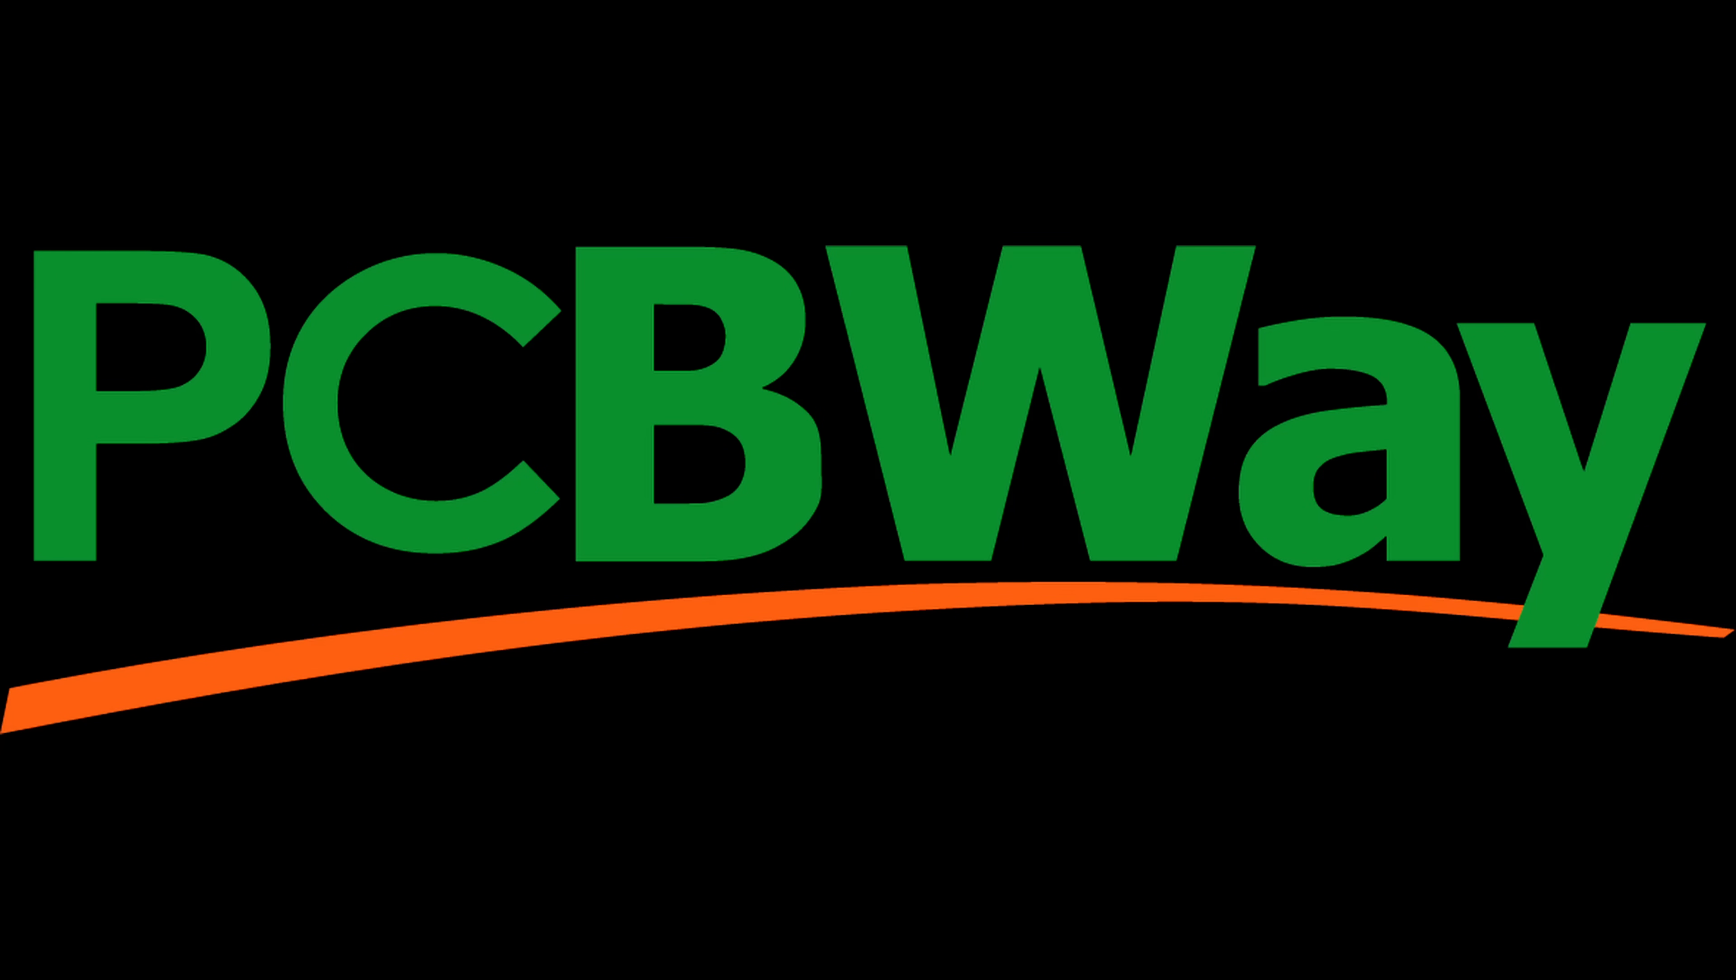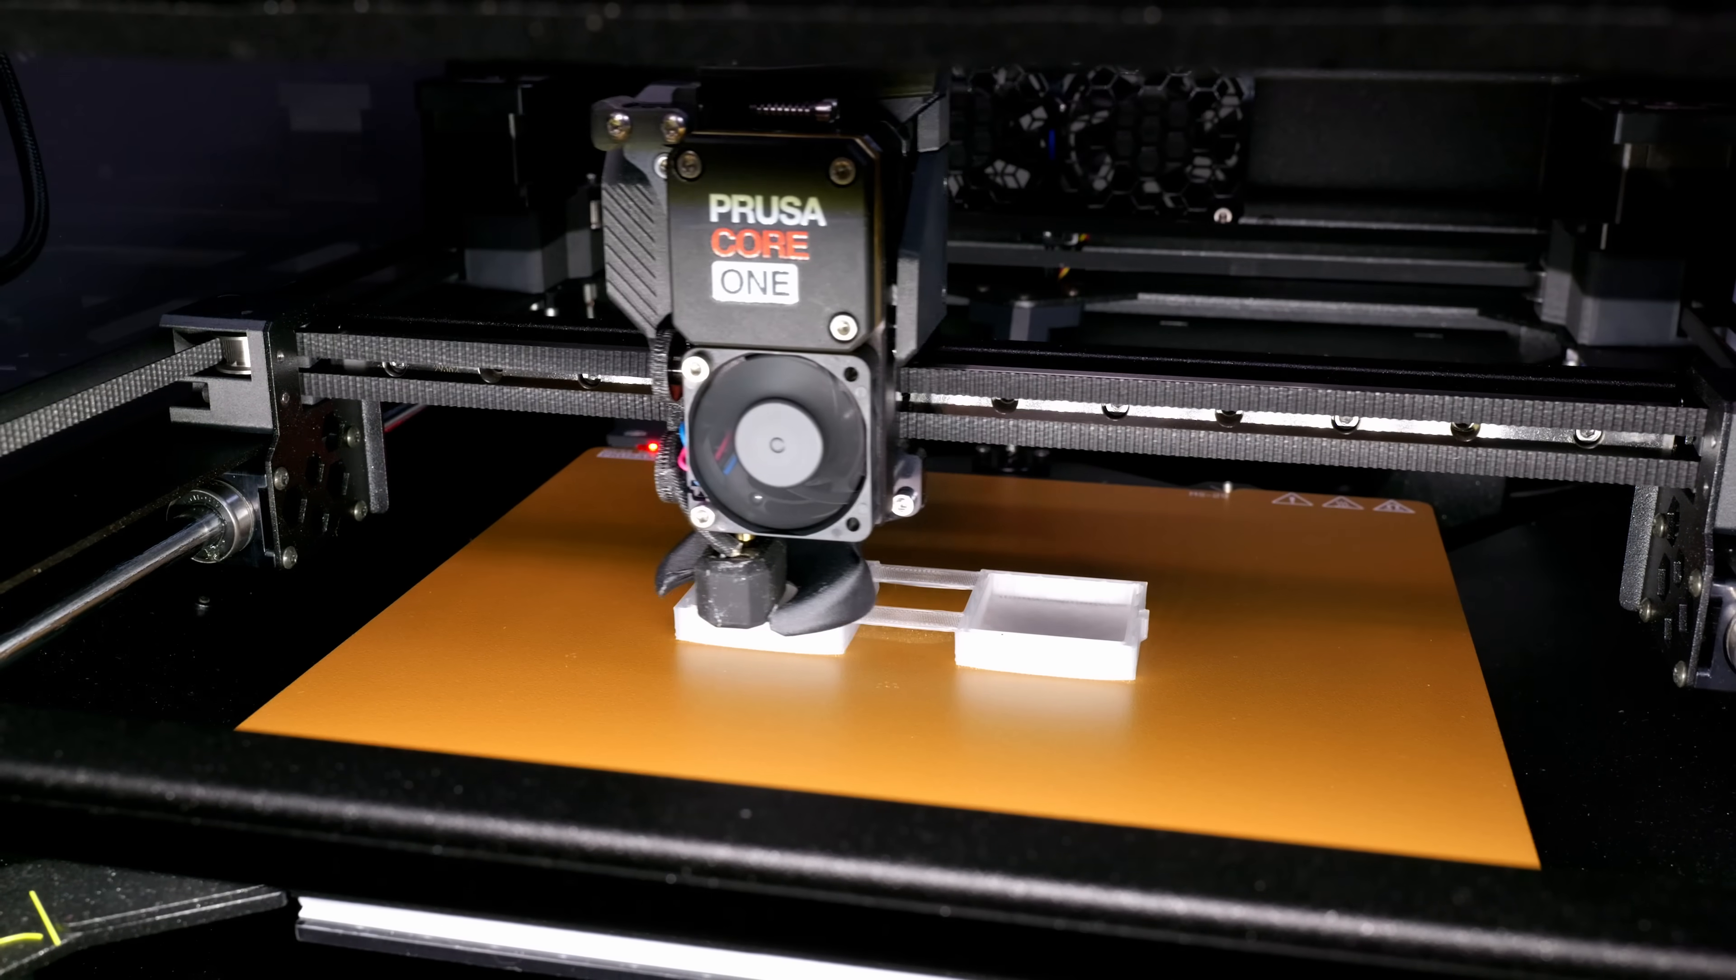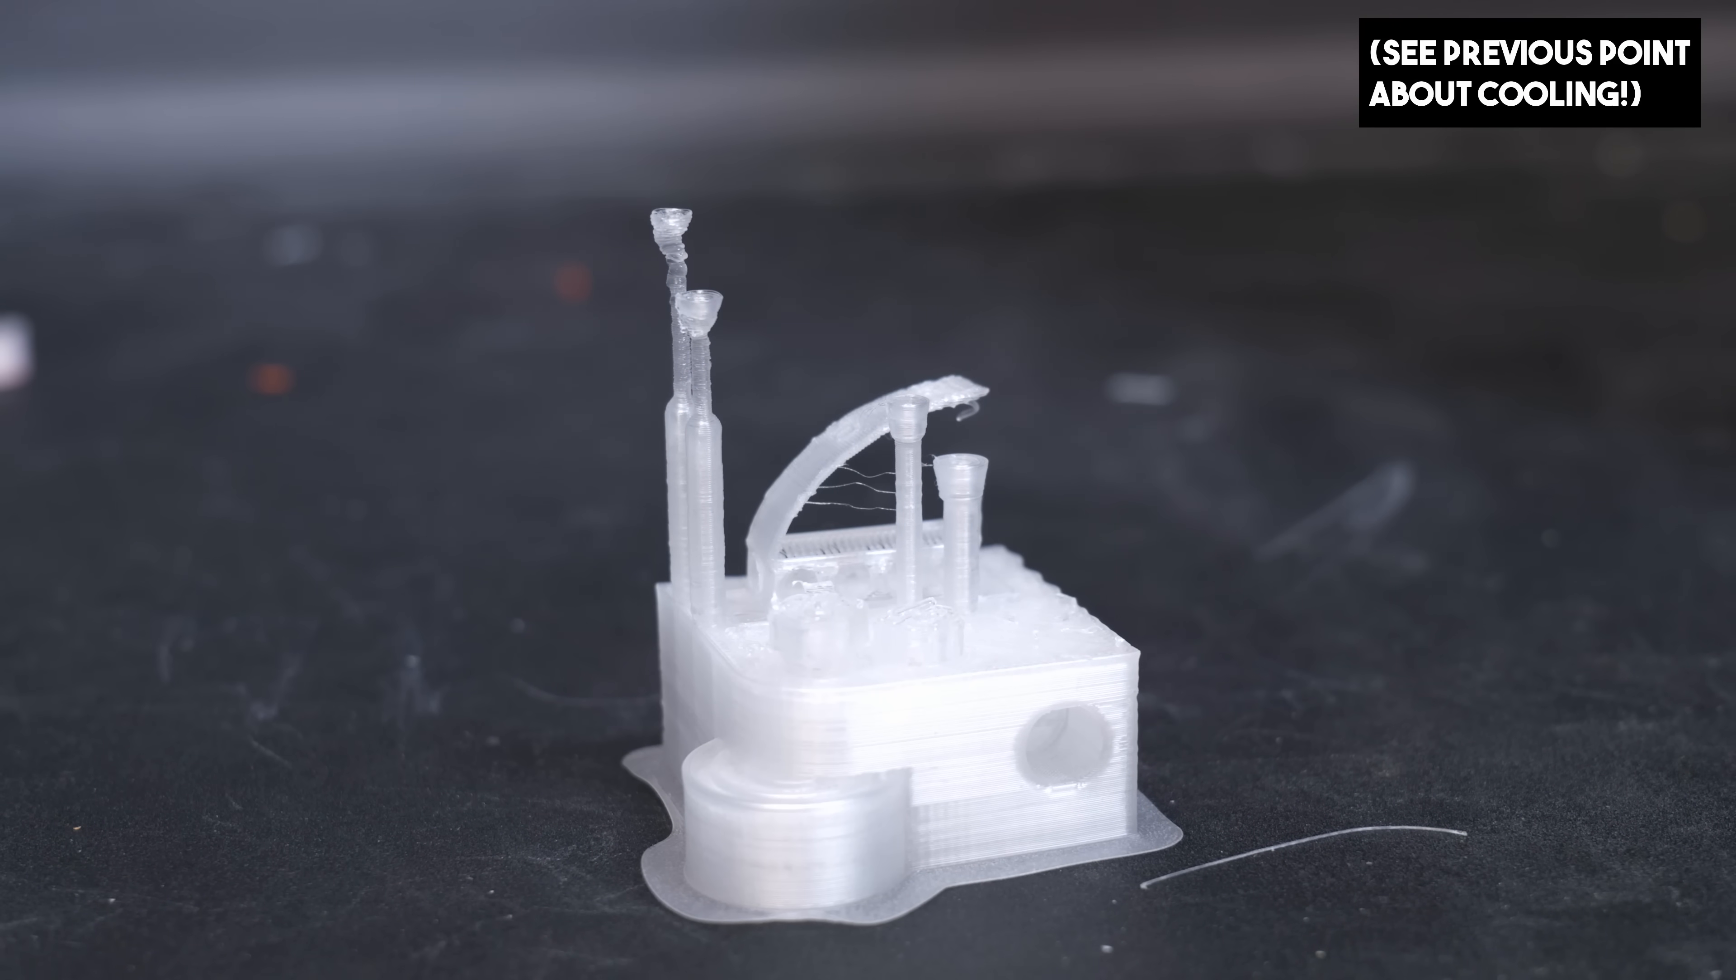Here's my calibration cube, it's not just useful for testing printers, which is what it was designed for, it also tells you a lot about materials. In the case of this Sunlu Polypropylene it's quite impressive, I think it comes out better than PETG, this was printed on the Prusa Core 1 and it uses a brim as you can see, and that's the first point I want to make which is always, always use a brim. You very rarely get away with not using brims on polypropylene, it's just not worth trying in my opinion. Conversely, if you use one of the bed surfaces I mentioned and you do use a brim, then it very rarely fails in my experience.